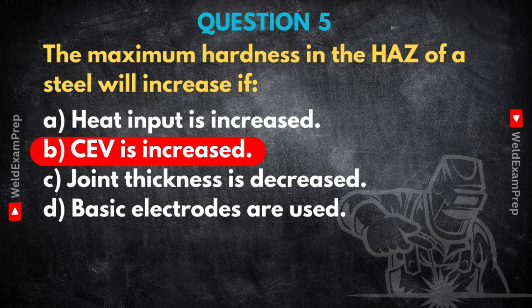They all contribute. So a higher CEV means the steel has a much greater tendency to form very hard, often brittle, microstructures, specifically things like martensite in the HAZ during that rapid cooling cycle typical of welding. More martensite means higher maximum hardness in the HAZ, and critically, a higher CEV significantly increases the risk of hydrogen-induced cracking, also known as cold cracking. Okay, so higher CEV equals higher hardenability equals harder HAZ equals higher risk.